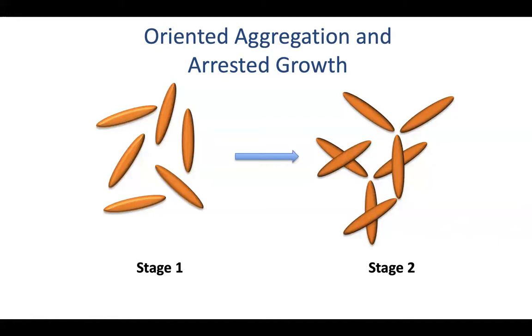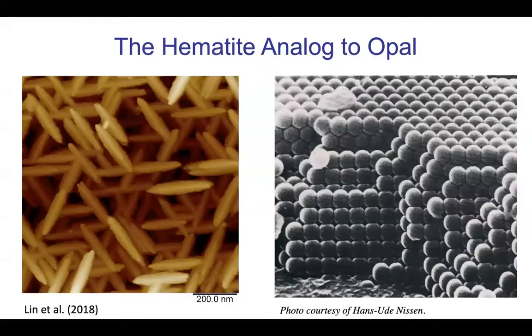So there's kind of energetically three equivalent orientations that these spindles can adopt as they attach to each other. And so what ends up happening is that you generate this kind of substructure, which we consider to be the iron oxide analog to opal. Instead of spheres that are micron scale and nesting together, we have these nanometer sized spindles that are aligning themselves in a crystallographically ordered way.